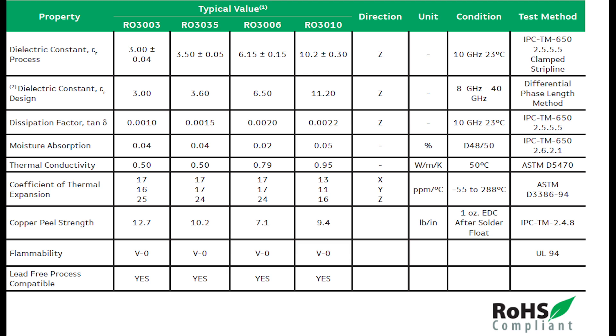These materials have dielectric constants controlled to a tightly controlled tolerance. Moisture absorption is another issue that comes up often in RF applications, where it can be detrimental to circuit performance. The moisture absorption values are very low — 0.04 or even less. Thermal conductivity can be important for thermal management; a value of 0.5 watts per meter K or greater is considered high thermal conductivity.